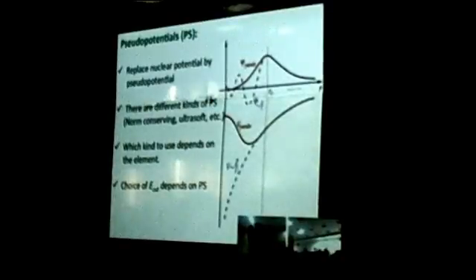So the ultrasoft pseudopotential proposed by David Vanderbilt, what he did is he relaxed the norm-conserving conditions, and as a result, I'm not going into details because that will itself require one full lecture, you can push the rc to higher values, and you can have softer potentials, and there are tricks by which you can get a similar level of accuracy.